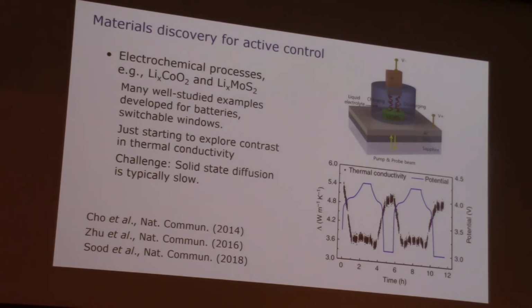It turns out this paper has actually gotten a lot of renewed attention right now because people care about what's happening to the thermal conductivity inside a battery when you charge it and discharge it. Because if you want to charge a battery really fast, you want to pull up to a filling station and do the equivalent of pumping gasoline into your tank, but doing it with electrical current, in 10 minutes or something, so you can go to the bathroom and get a cup of coffee and your car's charged. It turns out the thermal issues are really severe. And every bit matters, in terms of what the thermal transport is in the system.